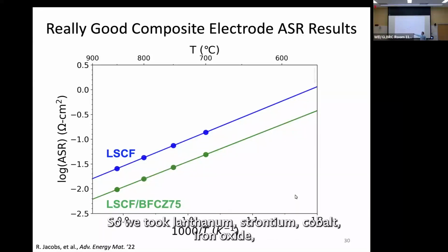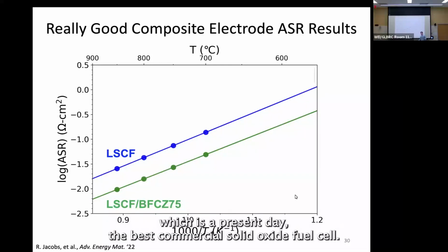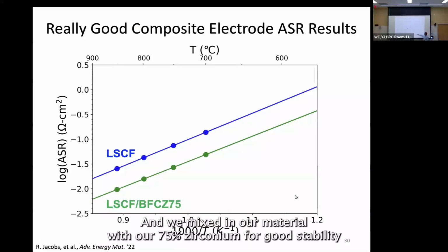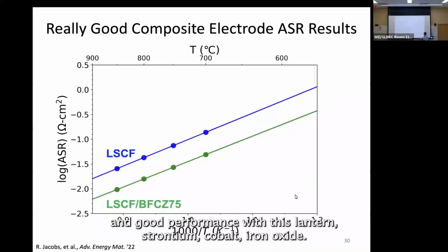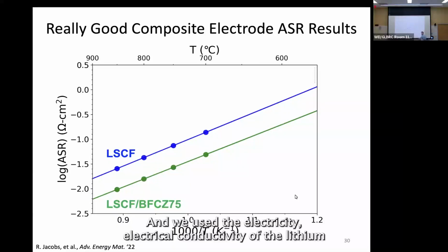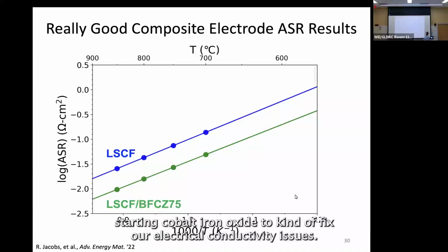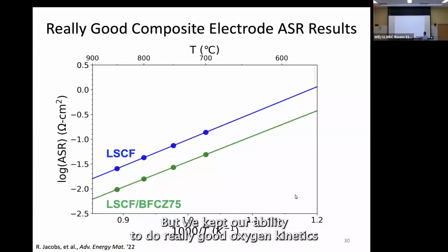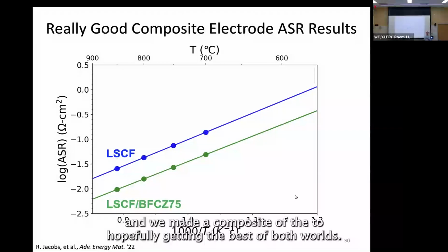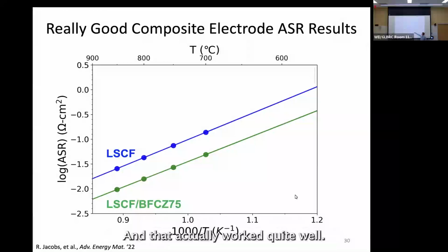So we took lanthanum, strontium, cobalt, iron oxide, which is the best present-day commercial solid oxide fuel cell material. And we mixed our material, with our 75% zirconium for good stability and good performance, with this lanthanum, strontium, cobalt, iron oxide. We used its electrical conductivity to fix our electrical conductivity issues, but we kept our ability to do really good oxygen kinetics. We made a composite of the two, hopefully getting the best of both worlds. And that actually worked quite well.